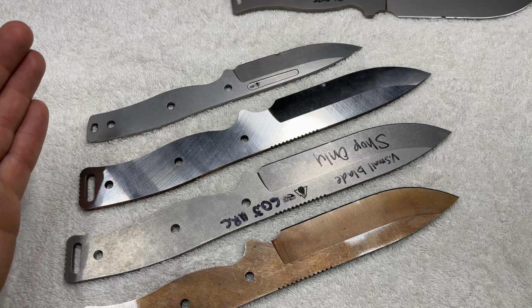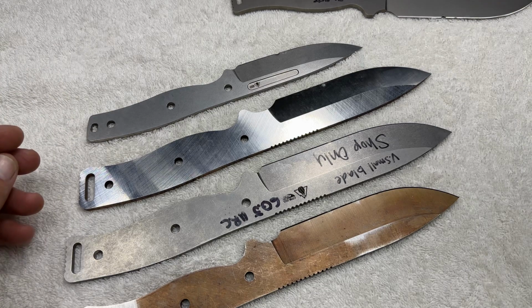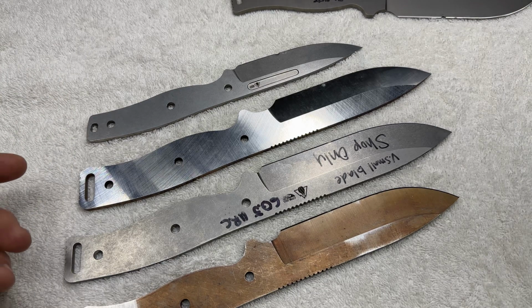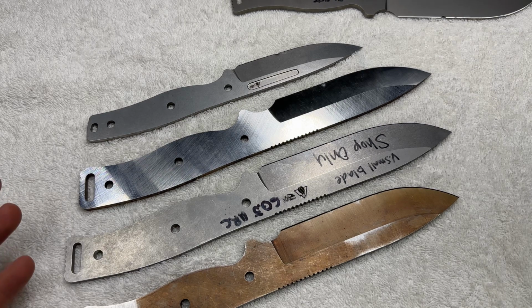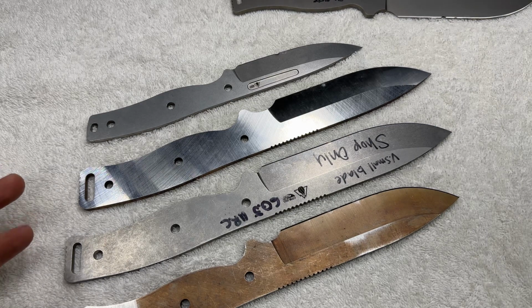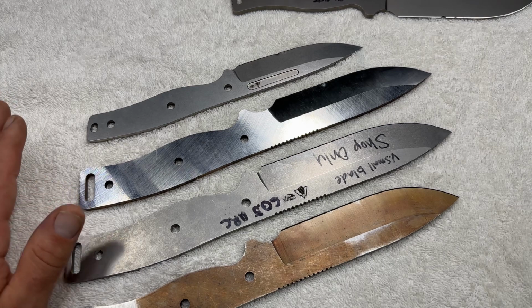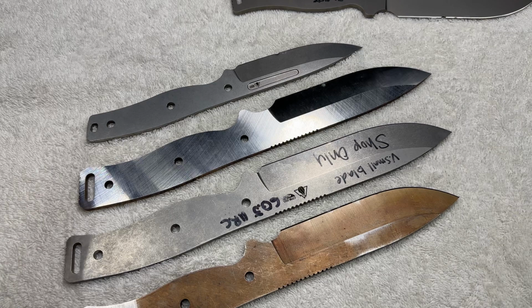There was a patent and some testing done back in the day for an improved 3V, but unfortunately Crucible went through a bankruptcy, and I think that just got dropped and forgotten, and they rolled back to this known standard. It's a great steel, but we need to get away from this mythology status of this material. It's wonderful, but there are some shortcomings with the longitudinal toughness and some of the structure at a microscopic level of the steel, where we could get an improved refined grain structure and better performance and less toughness disparity between the longitudinal and transverse values.